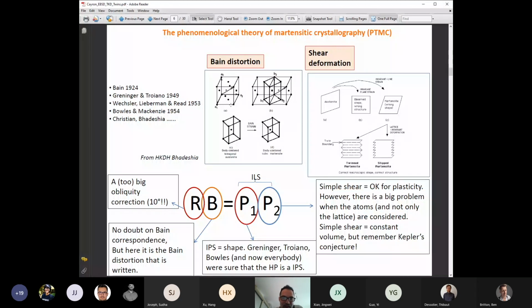So that's one point. And the other point is that we know from the shape that it is like a plate or a lenticle with an invariant plane, well, people think an invariant plane, in the middle of the lenticle. So they assume the distortion should actually be a simple shear, but since there is also a change of volume, it's a composition of simple shear and an extension perpendicular to the simple shear. So they have to introduce this P1, a matrix that is an invariant plane strain, a simple shear composed with a